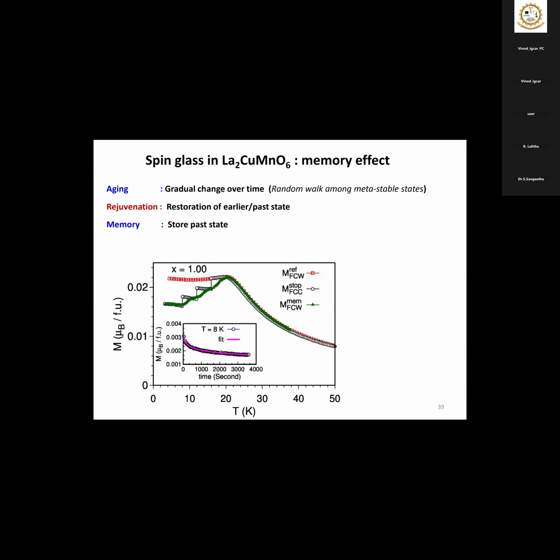You cool the material with a field cooled protocol. That will be the reference. Then you field cool again, and then you warm the material above your spin freezing temperature. That cusp or peak point is called the spin freezing temperature. Then you cool the sample again, and in between you stop, wait, and pause there for a few hours, say 1 hour or something, and switch off the field, so that you are switching off the field in the field cooled position.